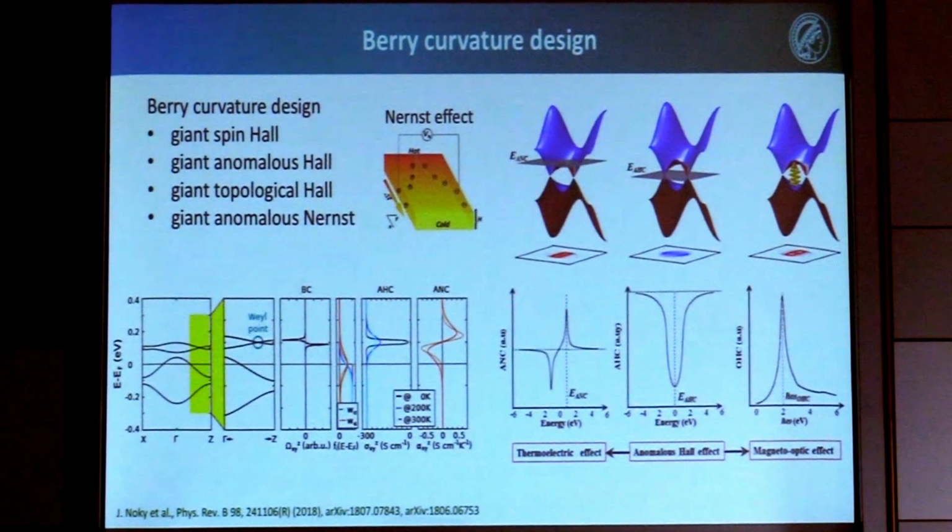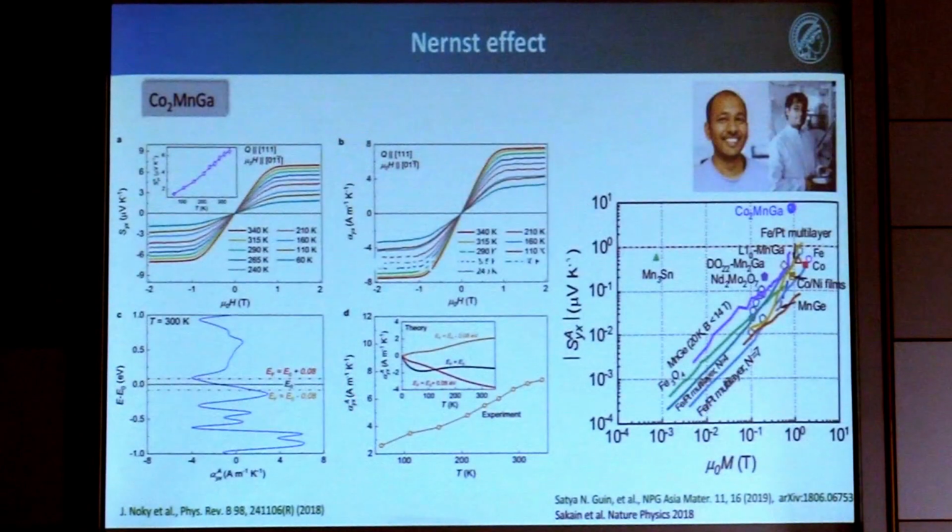They maybe can be useful for spintronics and maybe even energy conversion, because what we learned here in a toy model is that if we have crossing points in the band structure, we can conclude that we have a large Berry curvature, and we have a large anomalous Hall conductivity and a large anomalous Nernst conductivity. So nowadays we always do Hall measurements and Nernst measurements on these materials. And we even have large magneto-optical responses if we have this large Berry curvature. So even in some classical properties, we see unusual properties in this compound.